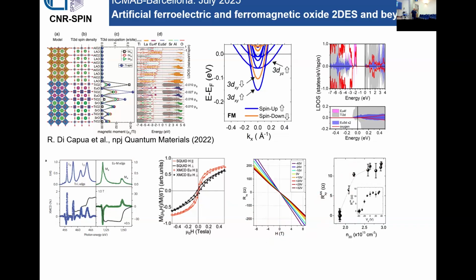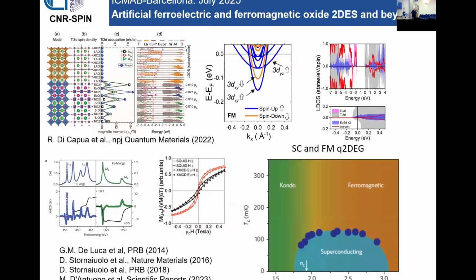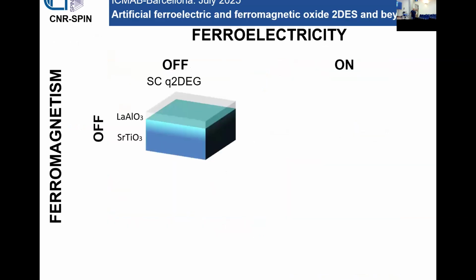But also, what was surprising is that the system also undergoes a superconducting transition, with a TC which is slightly lower, more or less half that of the LaAlO3 system. So it's a very exotic, I would say, two-dimensional electron gas, spin-polarized and superconducting.